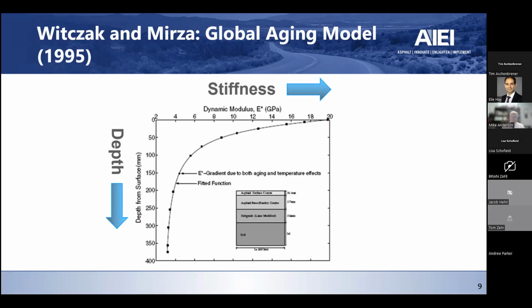The thing to note is that if you are close to the surface, the stiffness is quite high. As you get further down, about 100 millimeters or 4 inches down in the pavement surface, you can see the modulus is about a quarter of what it is at the surface. So this is 20 gigapascals. Down here would be closer to maybe 5 or 6 gigapascals. So there's a 3 to 5 times difference that we're looking at there.